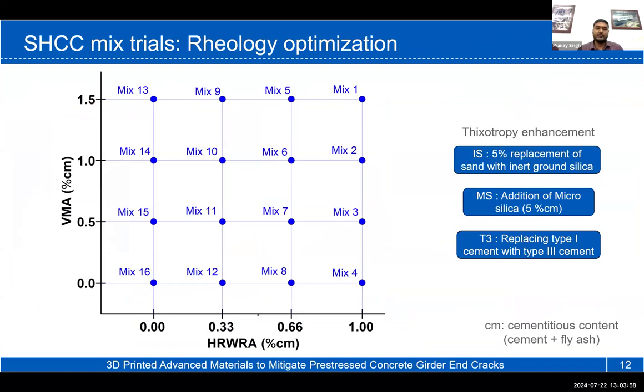So the first stage was viscosity modification. From the base mix, we created 16 different mixes with different VMA to HRWRA content. And out of these 16 mixes, we tested them, and we disqualified the mixes that were not showing printability, or showed water segregation or poor fiber dispersion. We have discussed it in detail in our previous April workshop, and I will not spend much time on that. Once we filtered out the mixes that were not printable out of these 16 mixes, the selected mixes were further optimized for their thixotropic enhancement by addition of ingredients like ground silica, microsilica, and type 3 cement.